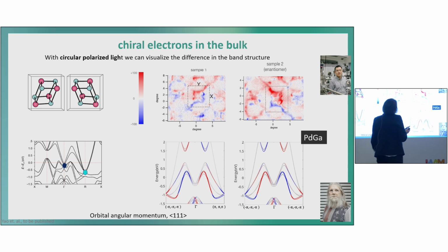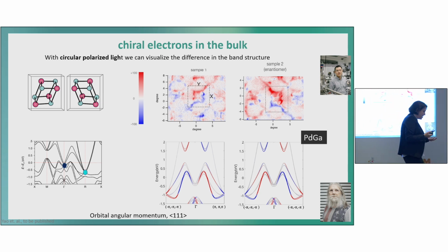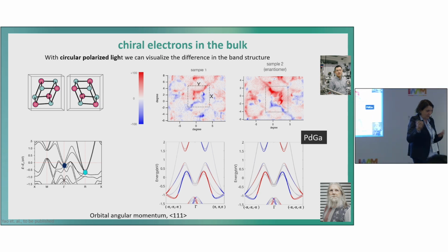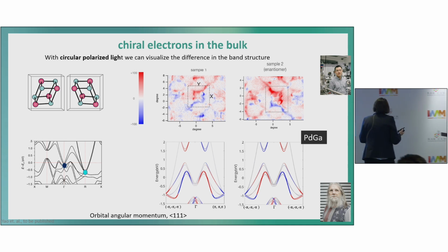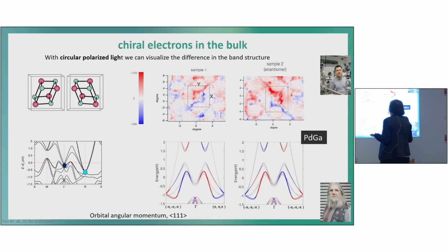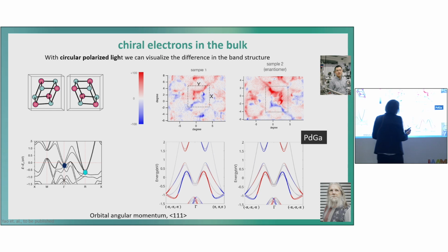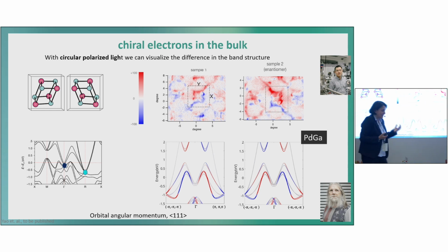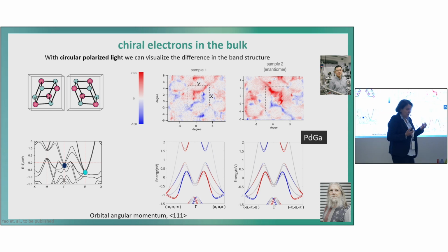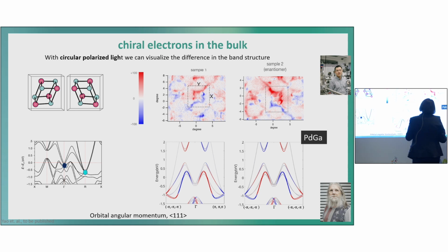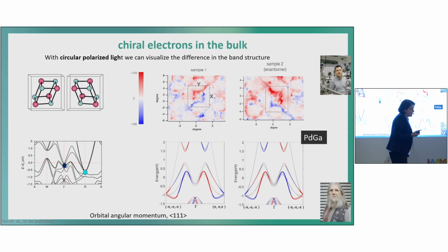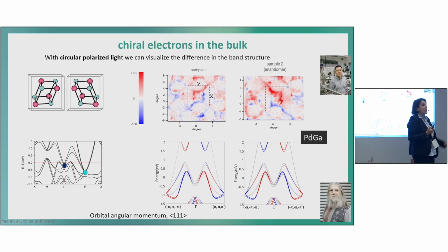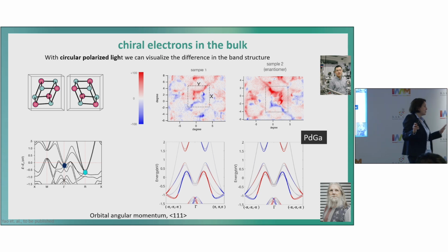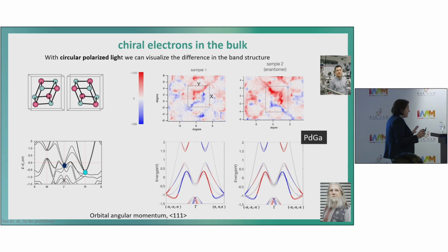Okay, the other thing is that the Berry curvature is also different, which is magic for the physicist, but not so interesting for the chemist. But the Berry curvature, this magic property, seems to be related to the orbital angular momentum, and therefore we calculated the orbital angular momentum again, also down there, for both chiralities, and you see they also behave like mirror pictures. So also there we see a difference.